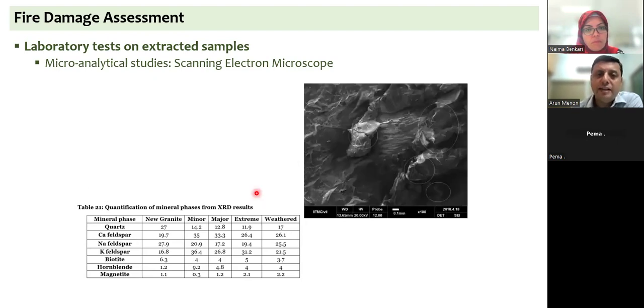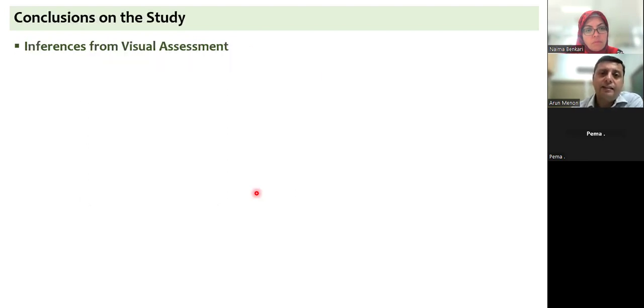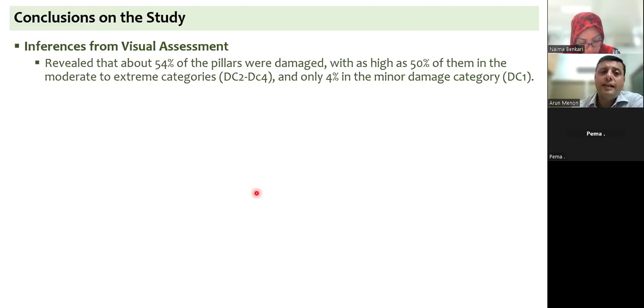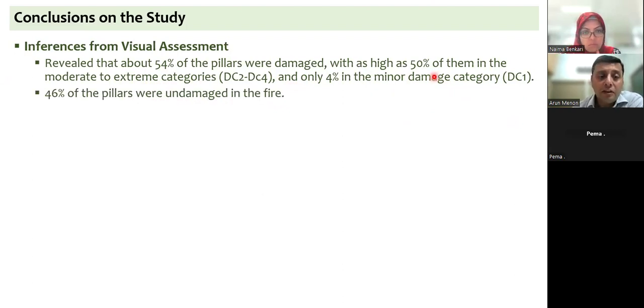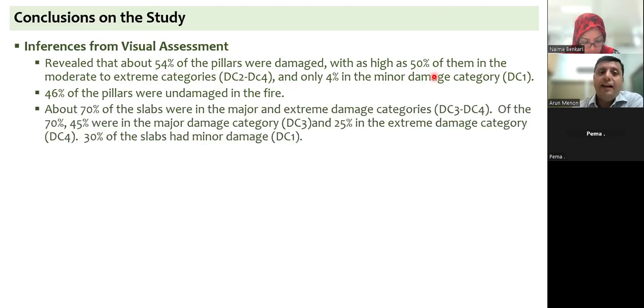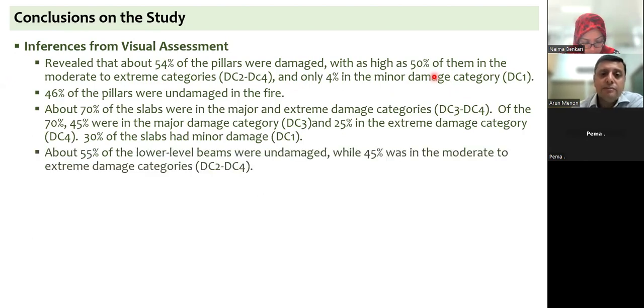These scanning electron microscope images plus the XRD and the other tests that were conducted, the non-destructive tests, along with the tests on the cubes, gave us some fundamental inferences. And I'll just take you through some of these inferences. From the visual assessment, we were able to arrive at the fact that about 54% of these pillars were damaged, and many of them were in the moderate damage to extreme damage category. So about 50% of the structure is in a bad condition, was clear. About 46% of the pillars were undamaged in the fire, and about 70% of slabs were in major and extreme damage condition, whereas in beams, about 45% was in extreme to moderate damage categories.